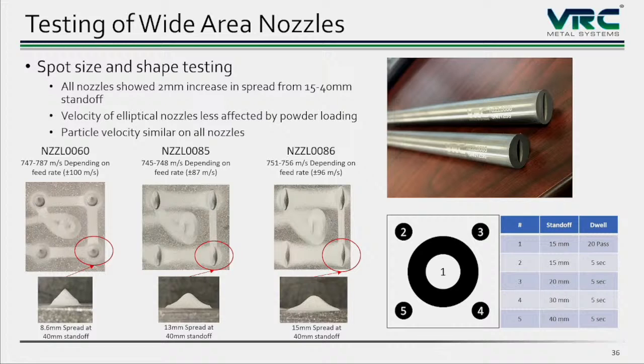All right, one of the first things we would look at is velocity, right? So if we look at the velocity of the particles, we have here a range for nozzle 60 and a much tighter range for 85 and 86, which are these two elliptical nozzles. The range of velocities that you see on the 60 is kind of interesting because the 787 meters per second is actually for a very lightly loaded stream, and if you load the stream up heavy, it drops down to 747. With nozzles 85 and 86, it didn't matter whether we loaded it heavy or light, we got the same result. We got 745 to 748, all within a margin of error here.